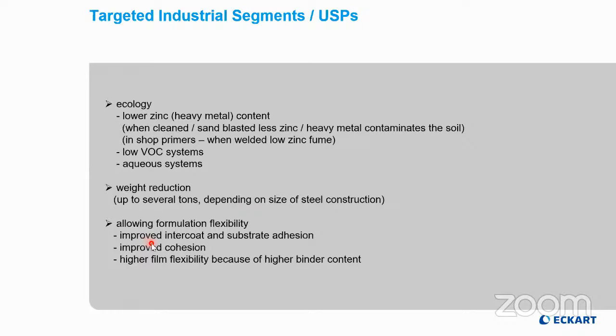With only 35% by weight, meaning around about 12% PVC, zinc flake in the formulation, you have about 65% of other components that you can introduce in the formulation, like binder, additive, or whatever solvent you want. And with a higher binder content, you increase your intercoat adhesion and the substrate adhesion of the zinc flake system. Using zinc dust primers, you have to use 85% zinc dust particles in the formulation, allowing you only 15% of other components in the formulation.